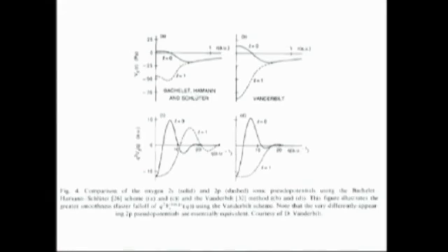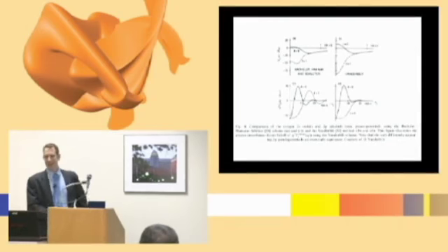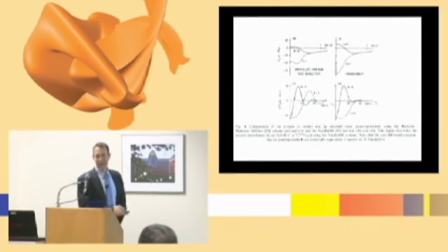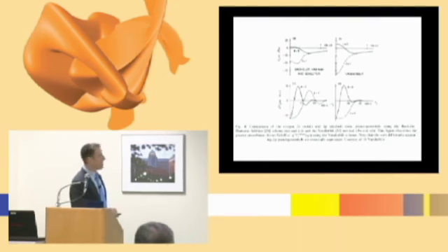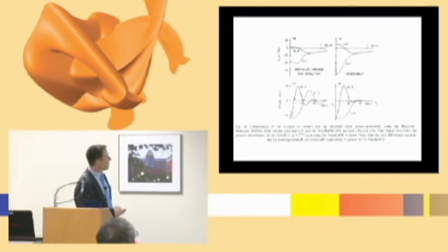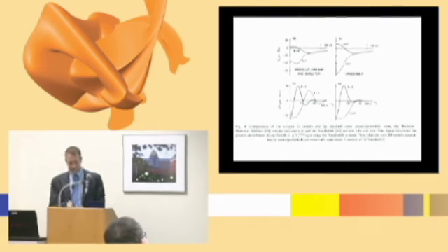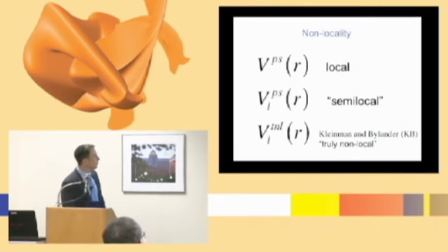And so literally there are, again, just like there are many, many different density functionals out there, many, many different choices of pseudopotentials. And you can make your own, and it's really an infinite set of possible pseudopotential choices to make for any system. And they will give different results. So this is a problem, because we tend to use pseudopotentials in QMC as well. You notice that if you take the Fourier transform of the pseudopotential, they may go to 0 at different rates, meaning that you need different sizes of basis sets to treat them, say, with plane waves.